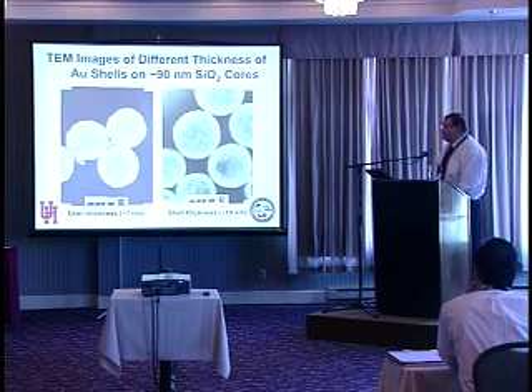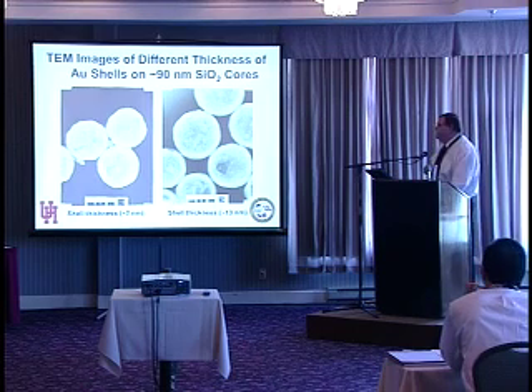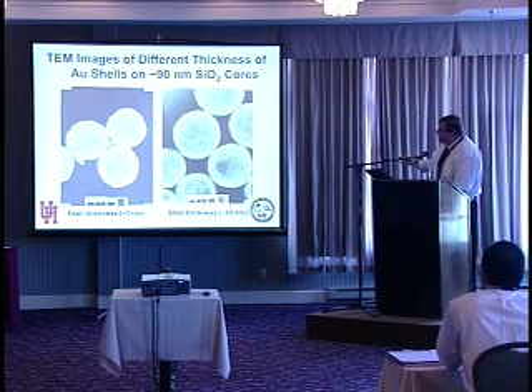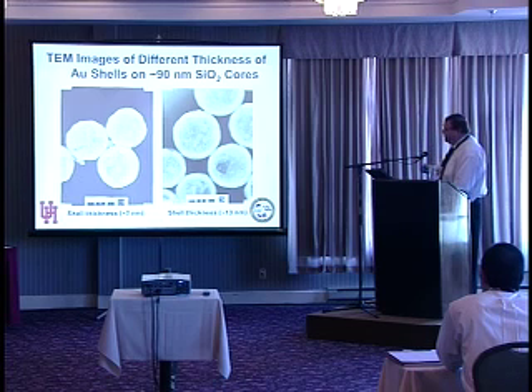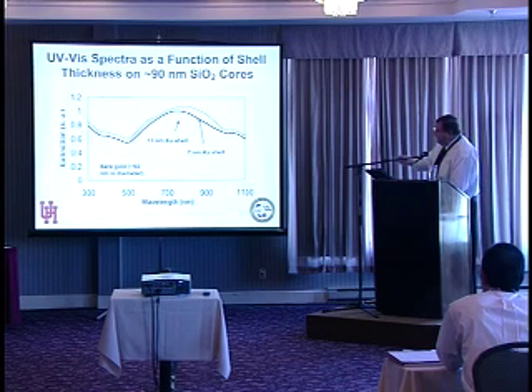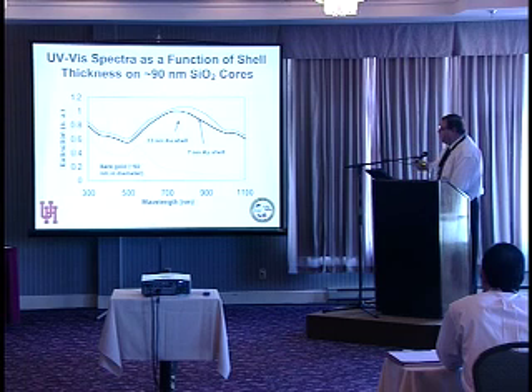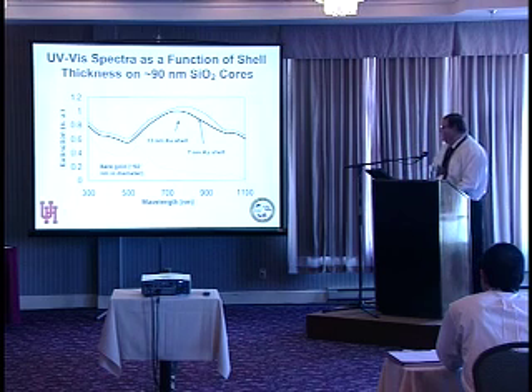We can make them smaller than 300 nanometers. Here are some 90 nanometer silica core particles, nanoshell particles, where we've grown the nanoshells on 90 nanometer silica cores. These particles have shells that are about 7 nanometers thick. These are about 13. And again, a simple gold nanoparticle would absorb at about 530 nanometers, but our particles are absorbing, for the 13 nanometer shell, at about 750 and around 800 for the 7 nanometer shell.